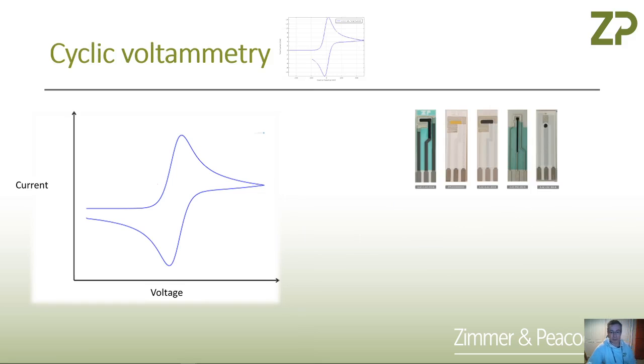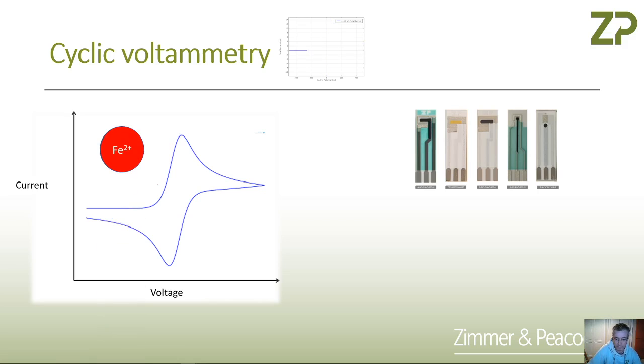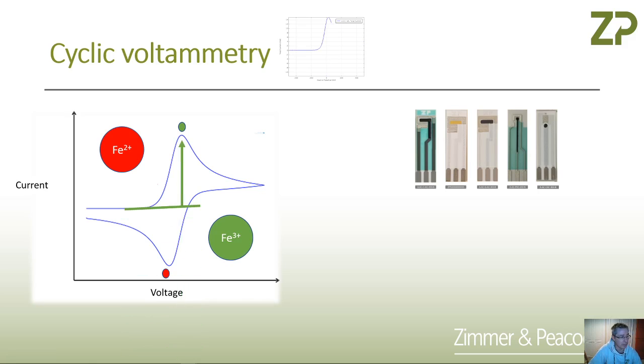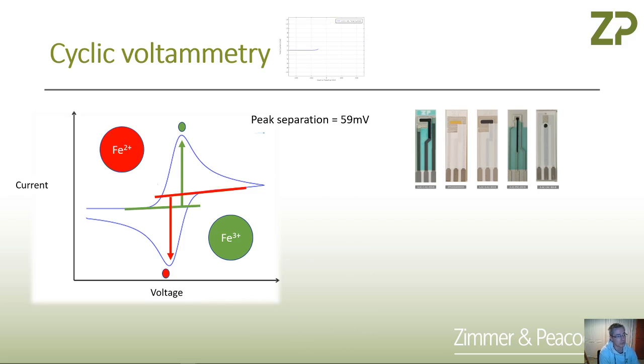What we do at Zimmer and Peacock is take our electrode material and expose it to a redox-active molecule. We do the oxidation of that molecule and then the reduction — for example, we might oxidize ferrocyanide at its oxidation peak and then reduce it. We characterize how the mediator is interacting with that electrode, measuring the peak height of oxidation and reduction. We also look at the difference between the two peak heights. For a one-electron oxidation-reduction, people expect a peak separation of 59 millivolts.